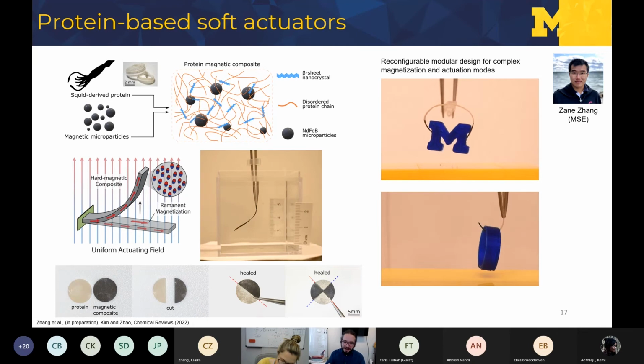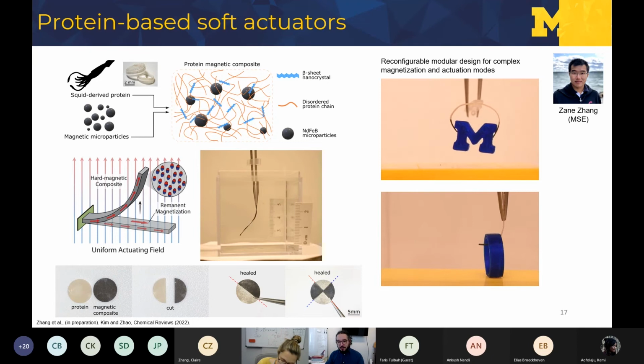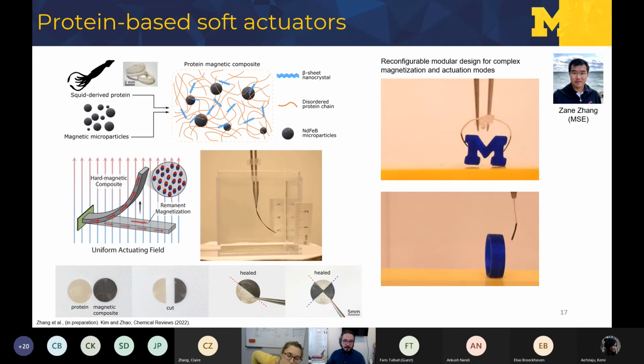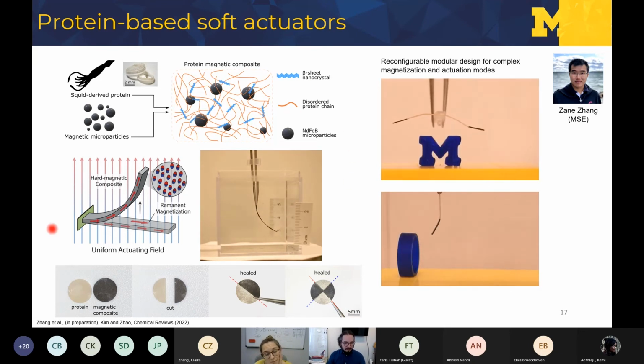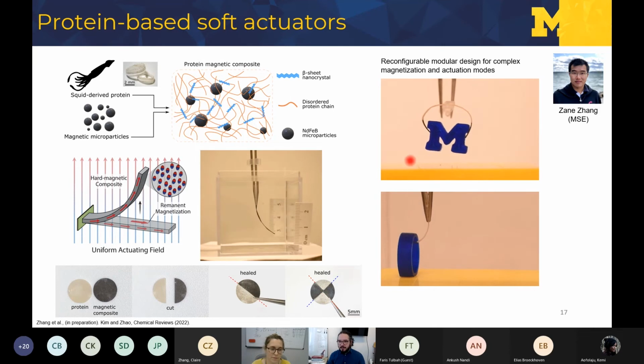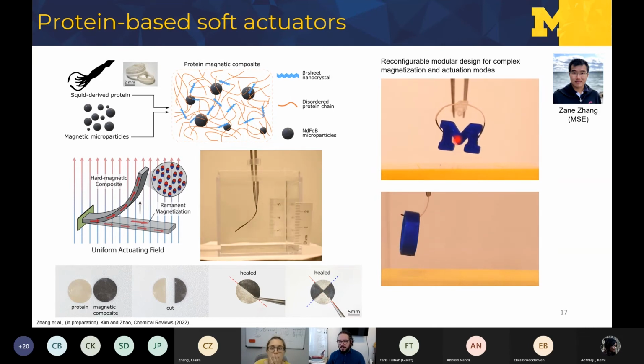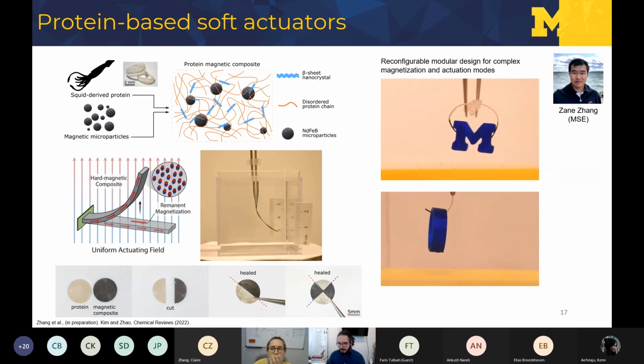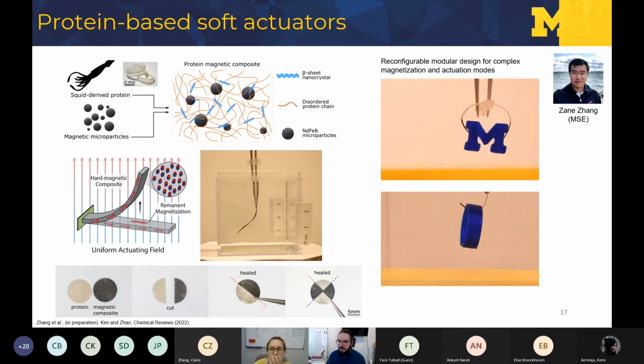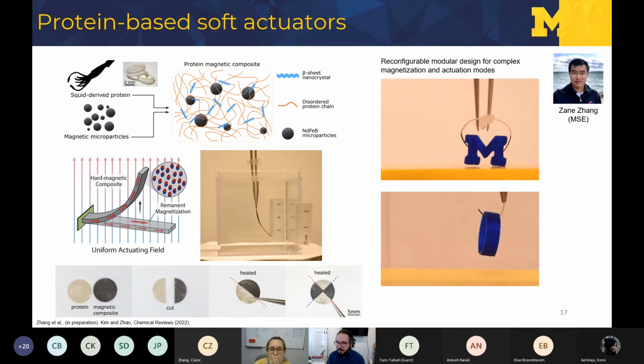So torque-driven bending, sorry. But what happens is once the magnetization is set, you can rewrite the magnetization, but it's hard to rearrange the particles inside the material, right? So we wanted to use these healing properties to reconfigure our materials so we can achieve very complex magnetization patterns that allow us to have some complex actuation modes, right? And we can change it and rearrange on demand, as we can see here. So we can have opposing ends from the same piece.